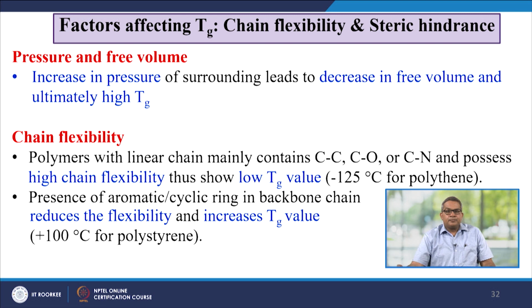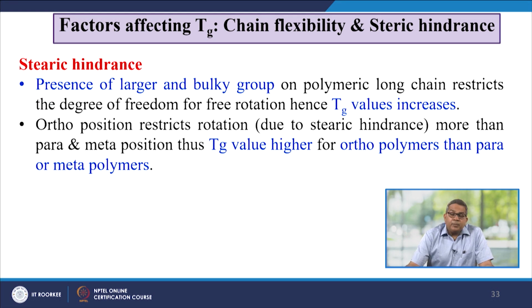The chain flexibility. A polymer with a linear chain, mainly consisting of C-C, C-O or C-N bonds, possesses high chain flexibility and therefore shows a low Tg value, usually minus 125 degrees Celsius for polyethylene. This is for the sake of an example. The presence of an aromatic ring in the backbone chain reduces the flexibility and thereby increases the glass transition temperature. Sometimes steric hindrance also plays a very vital role. The presence of larger and bulky groups on the polymeric long chain restricts the degree of freedom and free rotation, hence the Tg value increases. Ortho position restricts the rotation due to steric hindrance more than the para and meta positions, therefore the Tg value is higher.